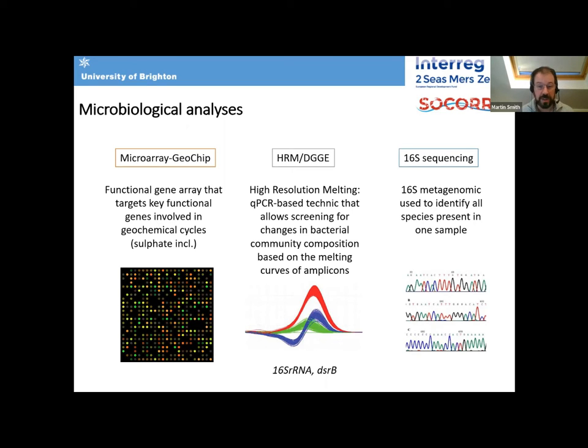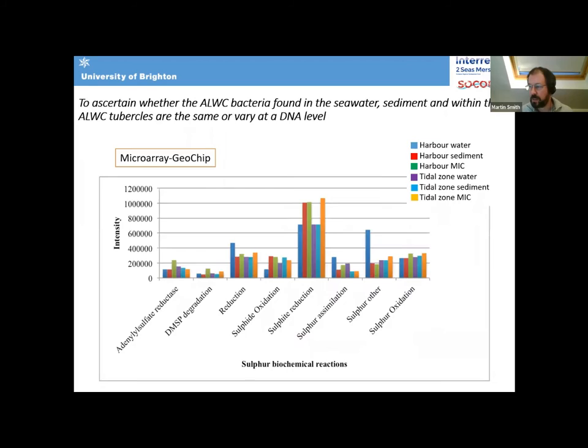It's a precursor to other techniques, but purely and simply in terms of the temperature profile, different microbial populations should have different melting curves. So we can use this alongside more detailed techniques to try and establish if we've got the same populations through a much wider range of samples. And this is something that hopefully we can develop into a rapid diagnostic technique.